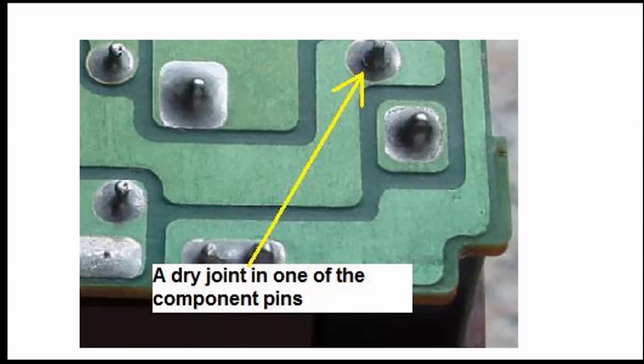The way I tend to think about mechanical shock is if you move a joint while it's cooling, then the solder comes in contact with either a bit of copper or a bit of component or a bit of soldering iron that isn't at the right temperature, and suddenly it gets cold. And if it gets cold, you get crystals forming. And if you get a crystal forming, then the remaining liquid is no longer the same composition as it was before. And because it's no longer the same composition, it's at another point in the phase diagram, and so another crystal will form. And now you've got two crystals and the stuff's out of phase, and you get more crystals forming. So it's a runaway thing, whereby once you start to get crystals forming, you're going to get a dry joint. But luckily, it's not a big problem.